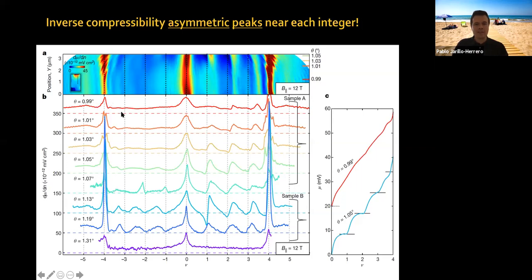So for 0.99 degrees, we just barely entered the magic angle range, okay? There are relatively few features, a little bit here, in the correlated flat bands. Whereas if you go to a twist angle, for example 1.13 degrees in this higher quality sample, or 1.07 or 1.05, you see these asymmetric peaks in inverse compressibility, and lots of features and lots of things happening.